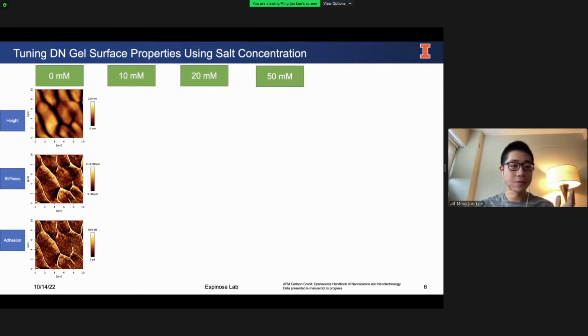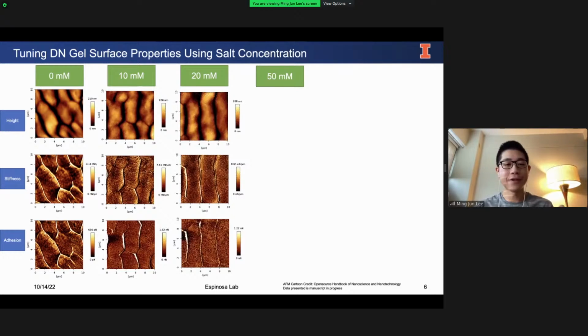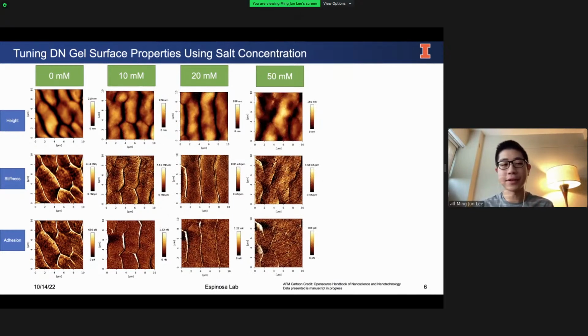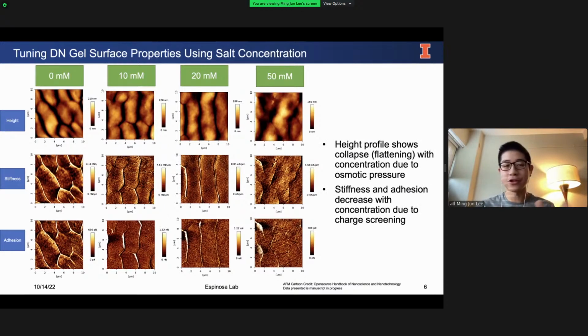And now I'd like to show you, moving from left to right, this one same hydrogel being equilibrated in different concentrations of potassium chloride salt solution. And what I'm seeing, a trend that appears, is that when the salt solution gets more and more concentrated, the height is actually decreasing. The gel is collapsing. And I think that this is due to the osmotic pressure differences. When the concentration is changing, water diffuses out of the hydrogel, leading to a volume collapse, volume going smaller.